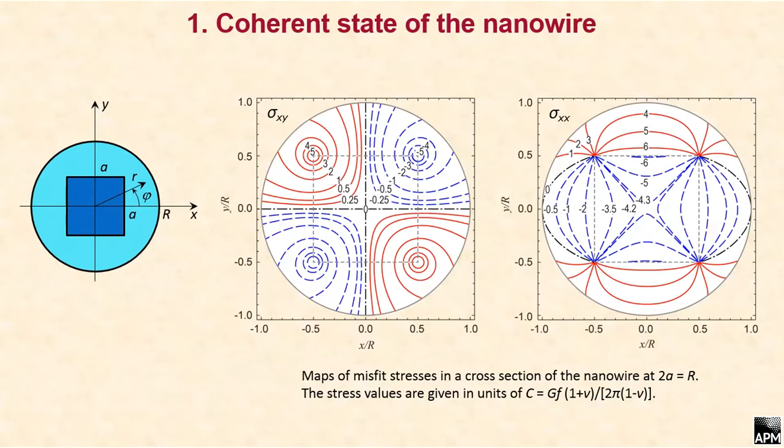And the first thing we can do is the space maps. Here, the stress tensor of this core inside this cylinder is given in Cartesian coordinates. And therefore, we see here the shear stress, which is concentrated, as could be predicted, at the edge of the core, right? Here we see some singular points and this logarithmic singularity, which of course may be eliminated by using, for example, a gradient theory of elasticity. But we will not concentrate on this point, but we can say that this point is very good for generation of misfit defects because the level of the stresses is very high. And also it's high on the surface, somewhere here.